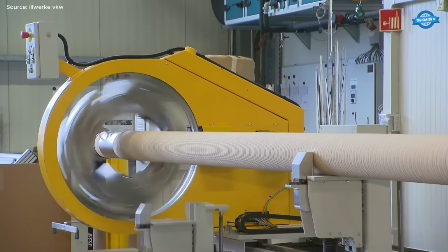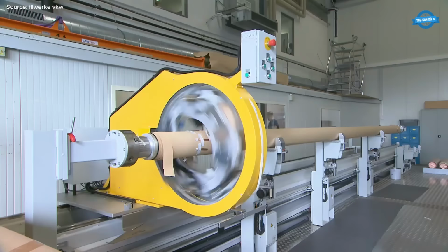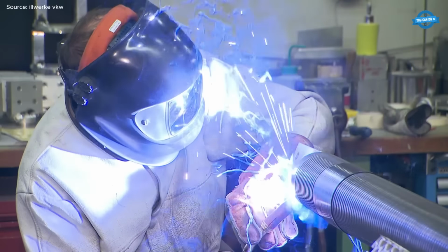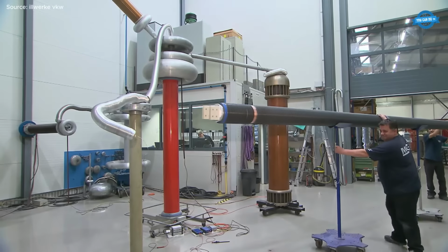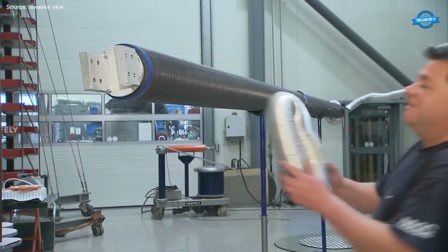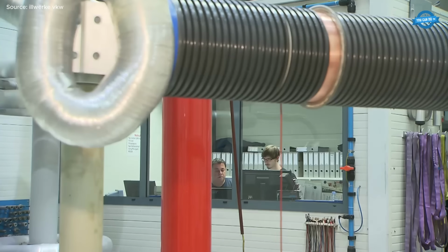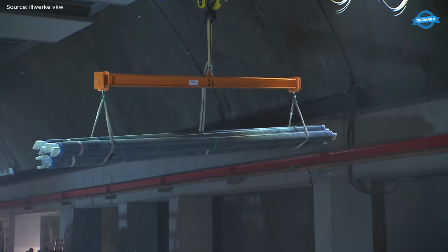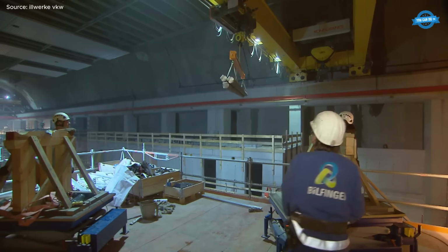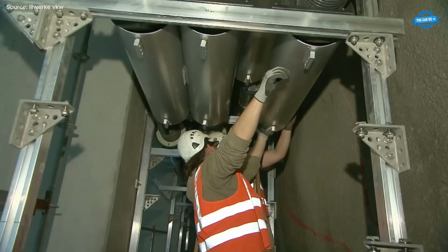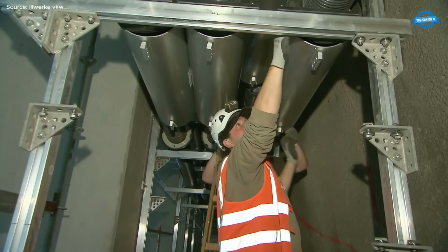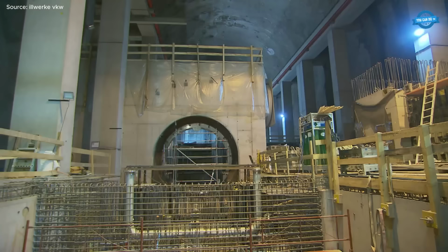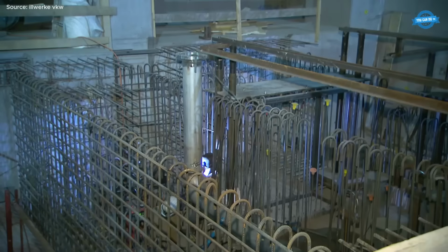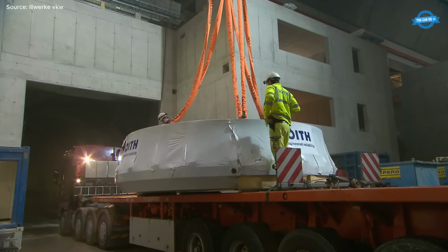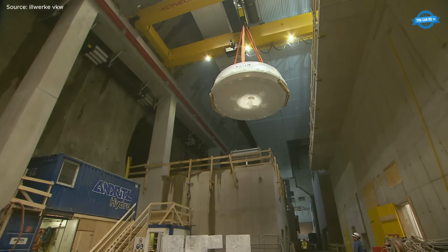Inside the cavern, the assembly of the first machine set is moving at high speed. The upper half of the stator, weighing 112 tons, is lowered onto the lower half. The rotor, with its 14 magnetic poles, each weighing 7 tons, is inserted with a tolerance of just 1 millimeter. This requires fingertip feel from the crane operators, as the total weight exceeds the capacity of a single crane, necessitating a tandem lift using both haul cranes.